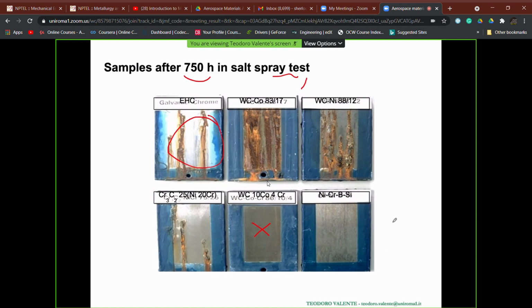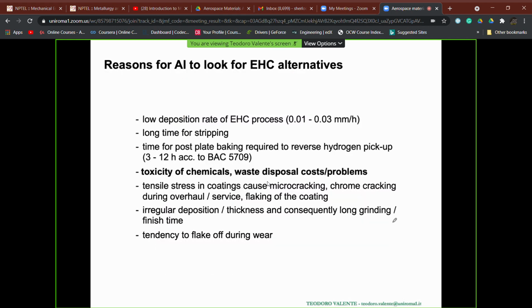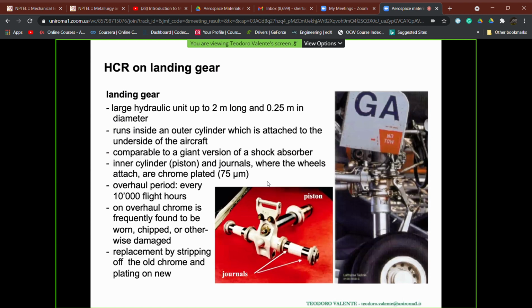Which is the message? The message is that a better performance can for sure be reached, but not for all the material compositions which can be used for HVOF. This work, in any case, has been done some years ago, in recent years, and so we already have the final testing qualification, and we know what we can select, what we must select in order to have the best results. And thus, landing gears can be coated in this area. You see, these are HVOF coatings.